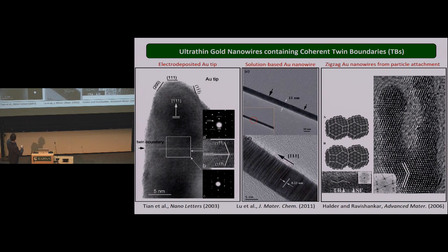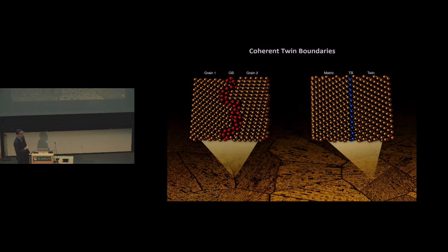Okay, so this is a large wire here made by electrodeposition. These ones are made by chemistry, and you see those little lines here represent those tiny interfaces. Okay, now what's very specific about the interfaces here, they are coherent, and that's very important for properties. So in material science, in the textbook, these twin boundaries are not new. And so I will explain here that another class of nanoscale metal, aside from nanowires, are what we call nanotwin metals. So nanotwin metals in particular are metals that include grain boundaries and grains. And those grains will contain a very high density of twin boundaries. So they contain nanotwins. And they are much larger than the nanowires. Okay, so another class of nanoscale metals I will discuss here are those nanotwin metals.